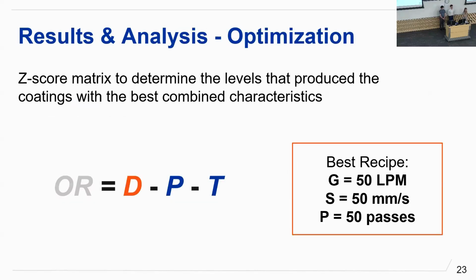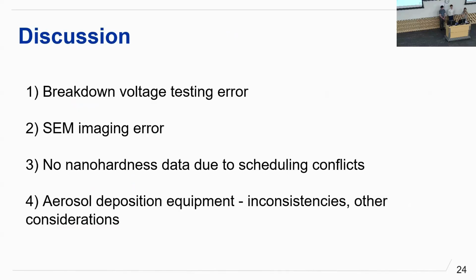So we wanted to optimize this recipe not just for each individual response, but also for the coating as a whole. So we created a z-score matrix using these DOE parameters to determine the levels that produce the coatings with the best combined characteristics. We input those z-scores into the metrics shown below and determined that the best recipe was when gas flow was 50 liters per minute, stage speed was 50 millimeters per second, and the number of deposition passes was 50.